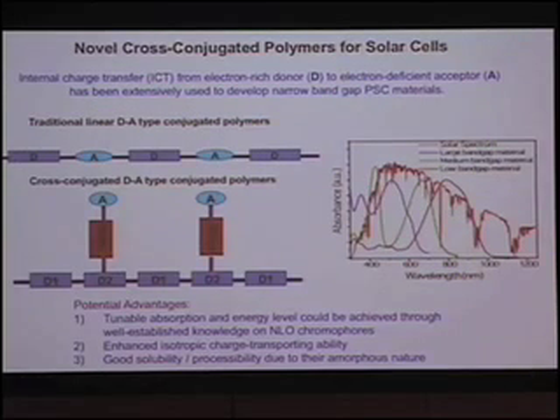And recently, we try to engineer a material that can cover the whole sun spectrum. Okay, we are actively developing so-called small bandgap conjugated materials, conjugated polymers. And the conventional approach in developing small bandgap conjugated polymers usually utilizes so-called donor-acceptor substituted conjugated polymers. Okay, and when you build this kind of material, because of the charge transfer property, you can build a small bandgap material and shift your absorption to the near IR range.